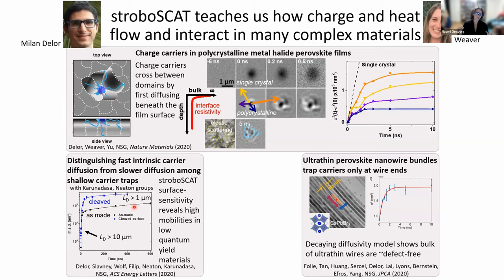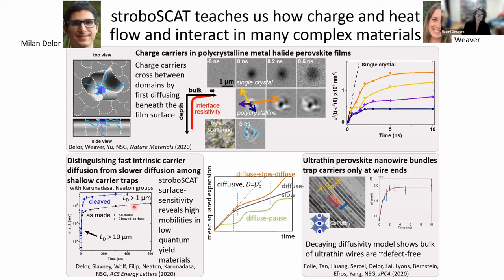What I mainly wanted to point out, looking at electronic forms of transport, is that there's a whole collection of different piecewise behaviors that we often see when following the mean squared expansion of the initial distribution. We're getting better and better at classifying them — whether we're seeing something larger in structure like grain boundaries, or something very small that's below our spatial resolution limit, but whose impact we can still observe.